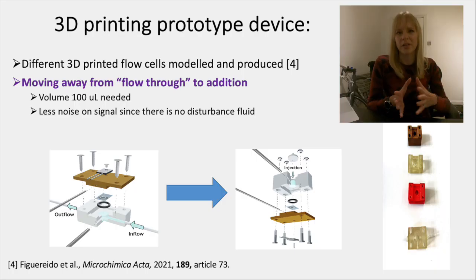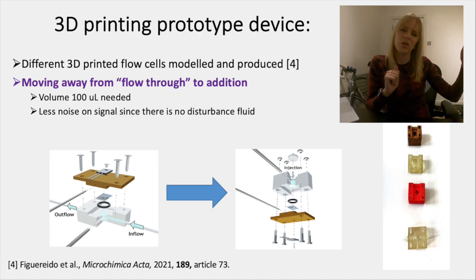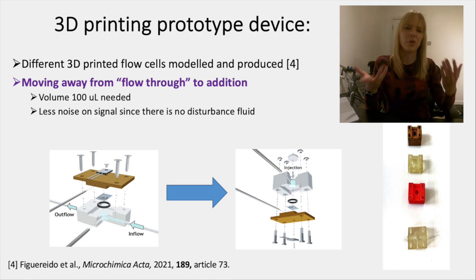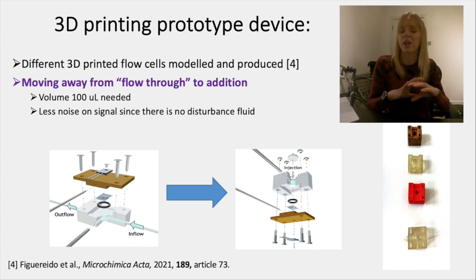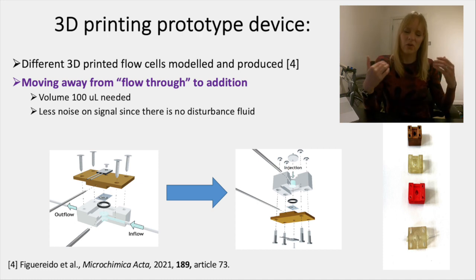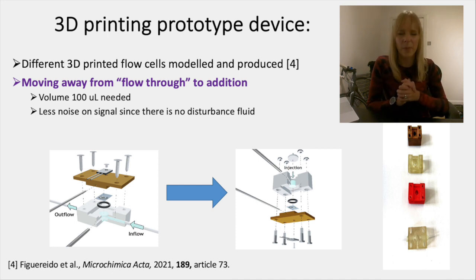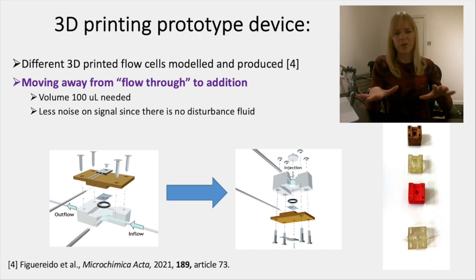So we had to redesign it to an addition type of setup where we actually only added the clinical samples with a pipette. And what we then figured out, and this is based on some modeling results that we looked at, is that because you're not flowing through the system, you actually have less movement in the system. So by adapting it to a system that's not moving, you also create less noise in the system. So it was like a twofold benefit. It was much better in terms of the clinical samples because we're able to measure really small volumes up to like 100 microliter. And it also reduced the noise because the liquid was completely still.